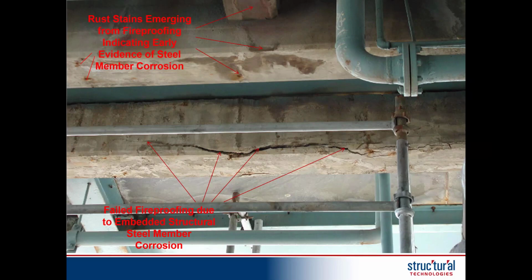You see towards the bottom of the slide, we see very large gaps, and we know that's actually wedging itself off of the underside of the bottom flange, and that's ready to fall, but yet the member next to it is just showing some very small indication that it's also following that same process, but very early in the process. We're starting to see some of the steel corrosion emanating through some of the cracks and potential conduits from the base of the cementitious concrete.